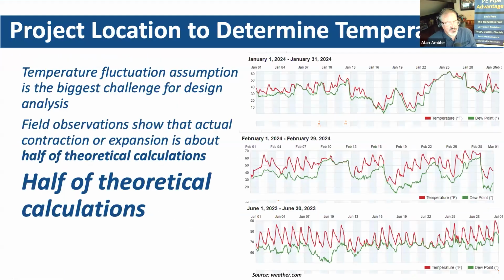So, Richard, this I added new for us. Whenever I look at an above ground project and start to go through the design analysis, I look at temperature fluctuation through weather.com or some other type of app like that. I'm looking to see what an above ground pipe may actually experience. Our literature that gives us the information and the equations to perform the calculation tells us that half of those theoretical calculations is typically what is observed as far as temperature fluctuation is concerned.